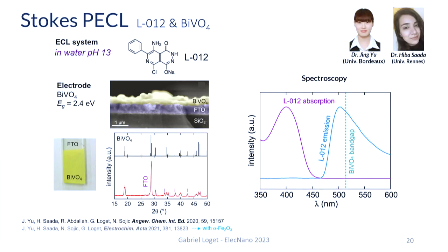If you remember, if we want to do PECL, then we have to excite this semiconductor in this region. So instead of using IR light, now we are going to use UV light. And you see the characteristic of the excitation we used. When we use this UV light as an excitation source, we are generating holes in bismuth vanadate, and this is what we want to do. But at the same time, as you can see, we are also going to excite our luminophore. So this luminophore is also going to fluoresce, which was not the case previously.